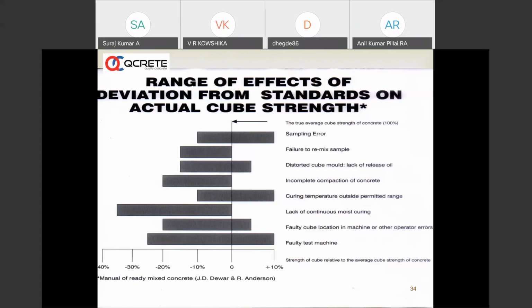For example, testing of steel or testing of any other material is all done in a third-party laboratory under proper supervision. But whenever we talk about the testing of cubes, many times it is done in old, faulty, uncalibrated machines, and curing is neglected. They don't cure at 27 plus or minus 2 degrees as specified in the Indian Standard. So what happens if the curing is not done properly? You will not have a proper strength.